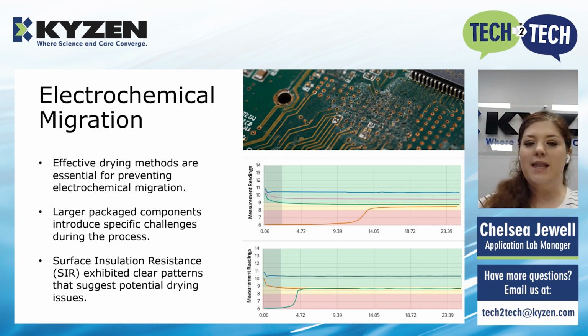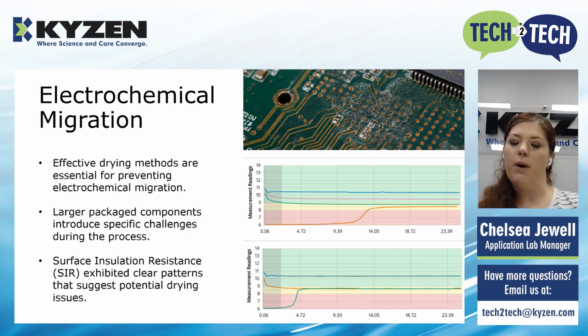Larger packaged components tend to have specific challenges with this. If you're looking at vented components, getting moisture in there in any aqueous process isn't a problem. It's how to get it back out and how to ensure that as you go on to your post-cleaning processes, that's a reliable component. You can look at covering those, masking those materials. We've also seen some instances with an IPA rinse. That's an option prior to a post bake out process. All of these factors can play into electrochemical migration and issues where you're seeing growth on the surface of the boards.